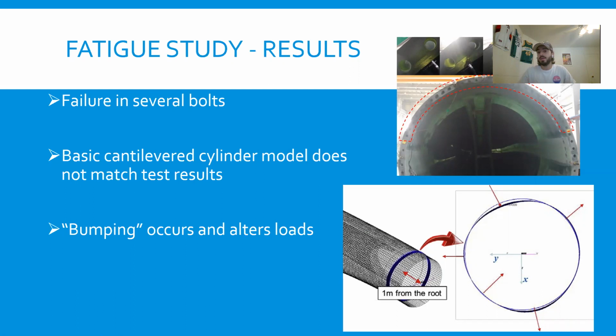So the traditional way of identifying what loads are expected at these bolts is with the basic cantilevered cylinder kind of model. However, that model does not predict the failure that was shown from the physical fatigue test. So that's what this study was about: to set out why this model does not line up and what is actually happening. So an FEA model was created using shell type elements. And from that, it was found that this effect of bumping occurs, as the research paper called it.